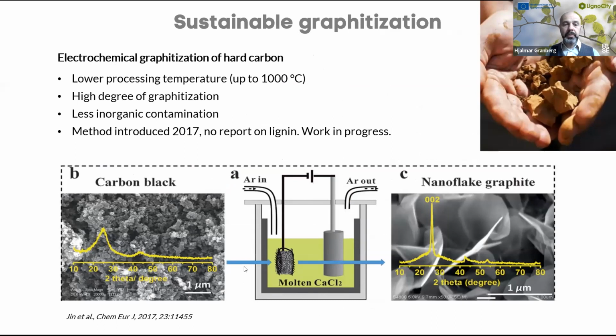So while you're heating up your sample, you're also driving a current through your precursor. It could be a lignin in this case. So that means you're introducing some kind of structure, and this ends up, if you do it right, as a graphite. And this can be done at low temperature. That's what we are doing. This is still work in progress, so I don't have the results to show you today.